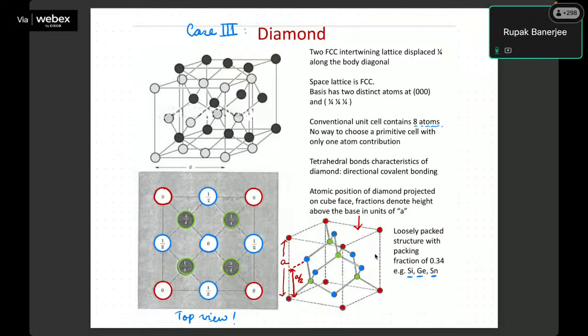But here you will see that instead of looking at it in a more complicated way, the case of diamond becomes much easier to visualize if you consider that there are actually two FCC lattices. One lattice is given by this gray dot, the other FCC is given by this black dot. If there are two FCC lattices that are intertwined with respect to each other, first you basically merge them together, then you pull them apart along the body diagonal in a direction of 1/4, 1/4, 1/4. So the one FCC lattice is shifted 1/4 along the body diagonal with respect to the pristine FCC, and this is the structure of a typical diamond. Okay, it is a double FCC structure. Space lattice is still FCC, but there are two FCC lattices which are intertwining.